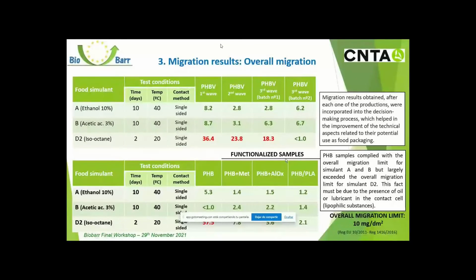And in this case, we have that PHB samples comply with the overall migration limit also for simulant A and for simulant B, but largely exceeded the overall migration limit for simulant D2. This may be due to the presence of oil and lubricant in the migration cell. But compared to functionalized samples, we observe that in this case there is a high decrease in the overall migration values, indicating that the surface treatment acts as a barrier to compounds.